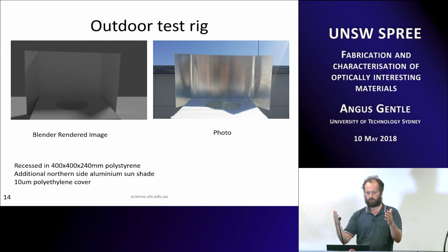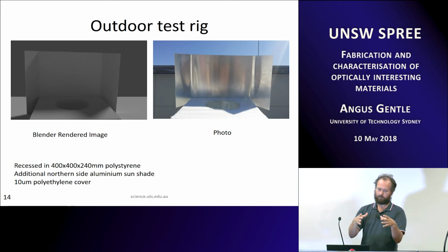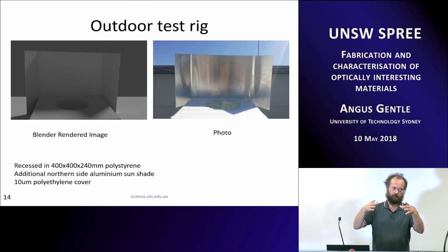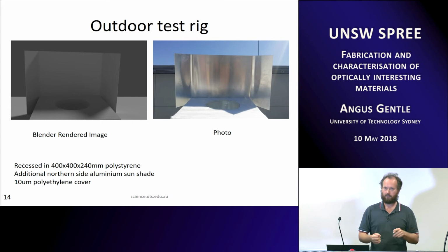So this one was set up with a front sunshade, so it's in diffuse only. Because one of the things about a parabolic reflector is that not only does it concentrate how much sky radiation is going out towards the sky, it also concentrates how much sunlight goes in, so that will increase as well. So if you do it in diffuse light, you can design it so that you get shadowing across the whole time. And so you can see quite reasonable agreement between those as well. We did a whole bunch of different models of looking at what area of the sky it actually sees. So does it actually reflect up and just see the top?